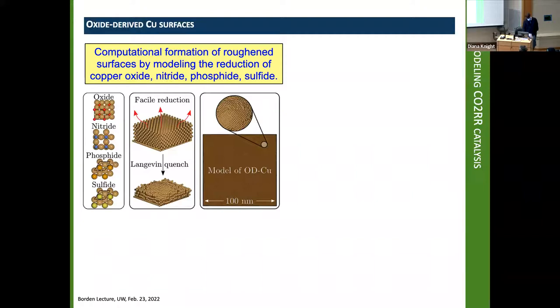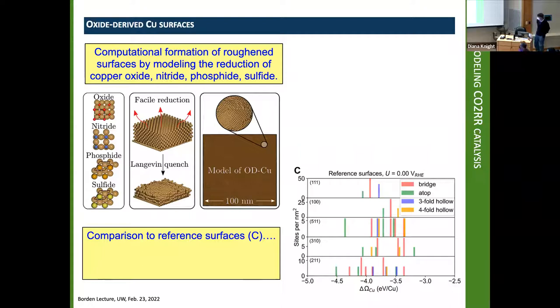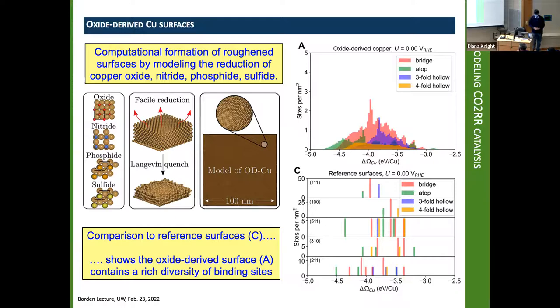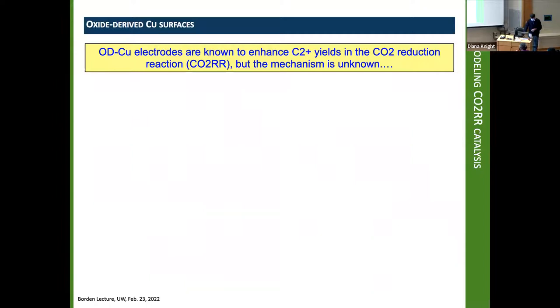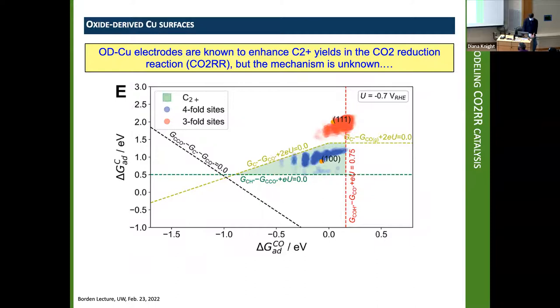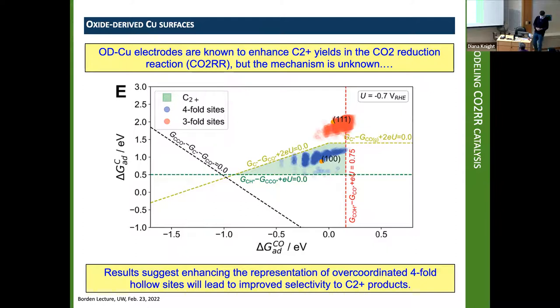In comparison to the reference surfaces, you then build an interesting distribution of sites that include not just the atop site, but a whole bunch of sites that lead you to a diversity of binding energies for copper, and the lower the binding energy for copper, very likely the higher the reactivity in terms of processing substrates coming from solution. So oxide-derived copper electrodes enhance C2 and higher yields. The mechanism is not fully known. And this is data that we produced showing that enhancing the representation of over-coordinated fourfold hollow sites leads to improved selectivity of C2+ products. So there are some possible design principles for better catalysts here, and much more still to be done. So that's a hint of what can be done that way.